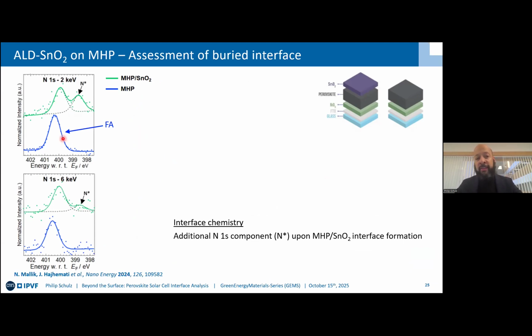In blue, here you see the nitrogen peak coming from MHP. And it's still preserved once you go to the system where you have the tin oxide on top, but you also see the rise of an additional core level here, denoted as N star, that is more pronounced in the 2 kV compared to 6 kV, meaning that it is mostly located at the interface.